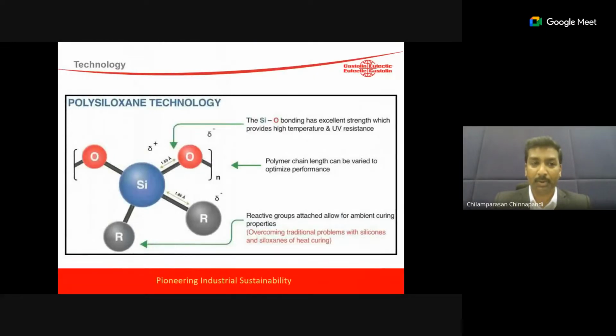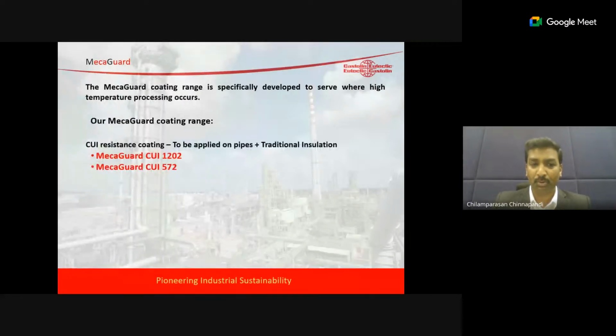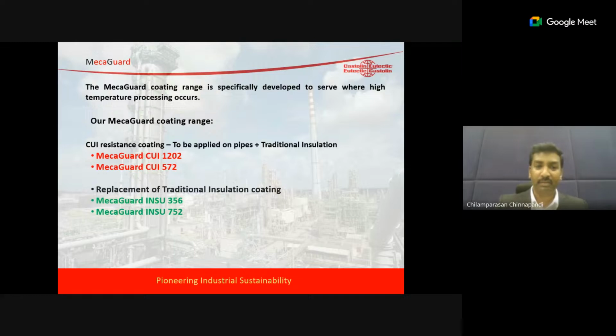With our polysiloxane technology, we have two products which can give you a coating outside the pipe. Then you can go for the traditional insulation, so you can completely avoid corrosion. Then we have the new technology called MecaGuard insulation coatings, where our 356 and 752 can be used up to 400 degrees for pipes for material transportation where the heat is required within the pipe. This can keep the temperature within the pipe.